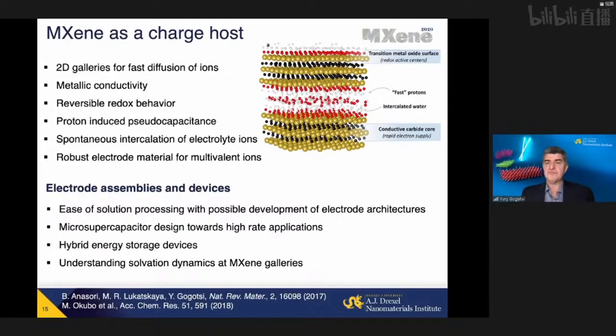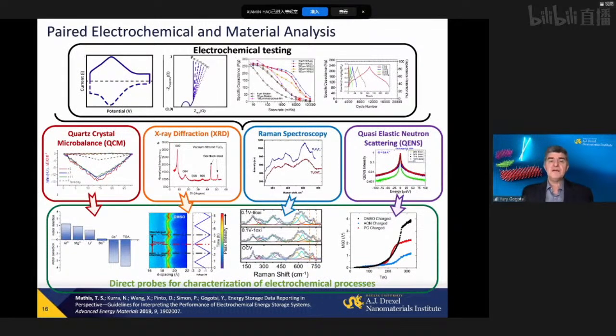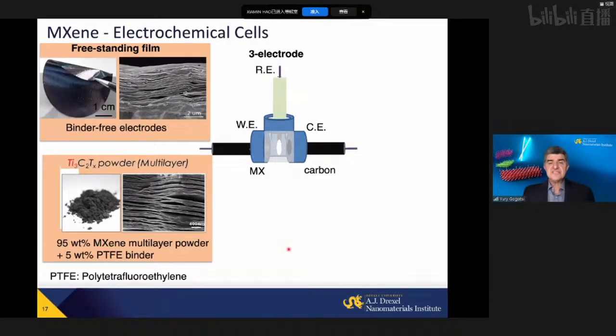I'm going to give a couple of examples, first on aqueous systems. We start with intercalated water just after synthesis, and we have protons there. But there is, of course, the possibility to use organic electrolytes, ionic liquid electrolytes, and work with lithium, sodium, potassium, and other elements. What we do in my lab is first electrochemical characterization: cyclic voltammetry, galvanostatic charge-discharge, and electrochemical impedance spectroscopy. Then we look in situ, studying the mechanisms of processes to understand what is going on when ions go in MXene. Are there redox reactions? Is there charge transfer?